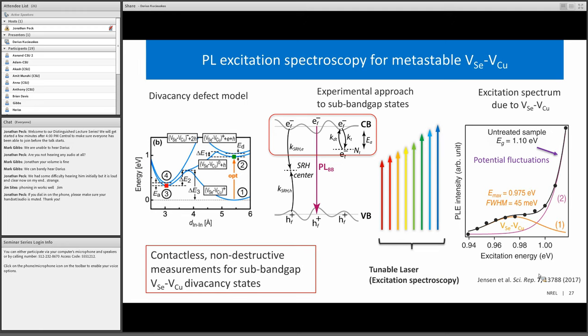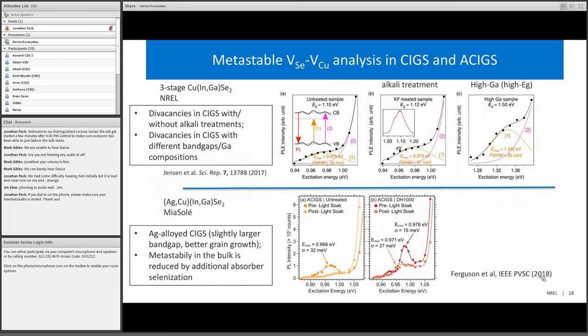This is a pretty general observation, in that we can look at CIGS grown in a three-stage process with or without alkali treatments, for the CIGS band gap of about 1.1 eV or 1.5 eV, and these defects are still observed and present and can be quantified with the excitation spectroscopy.